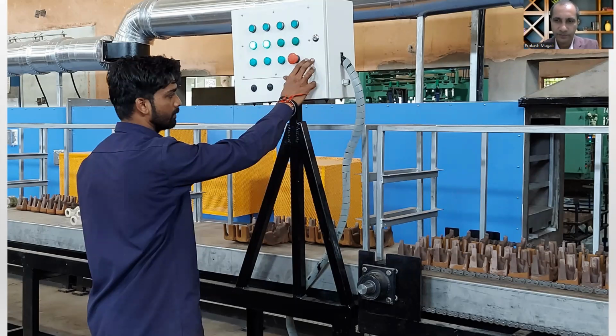My last question: is there any change in the color when we pass the core through the oven after drying? Is there any change in what? Color, color of the core. No. So that is again one of the advantages you can say. It will become slightly darker for sure because you're heating it to a certain temperature. But because microwave heating does not burn and it is attacking only the moisture and not the sand heating, your color does not change majorly. It remains almost the same. And there will not be any peel off or rubbing. No, nothing. The sand will not get looser.